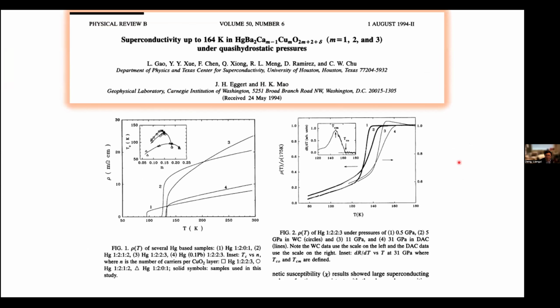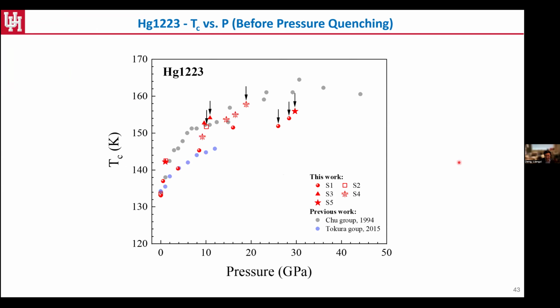And also back in 1994, in collaboration with David Mao's group, Paul Chu further pushed the TC up to 164 Kelvin. And that was the record until the hydrides kicked in, right? So now we're going back to this material again, the cuprate mercury 1223. First of all, we're trying to reproduce the TC under pressure. Honestly, we were not that lucky to hit 164, but we were able to get above 150, close to 160. So we're trying to quench, of course, from those high TC we reached under high pressure.